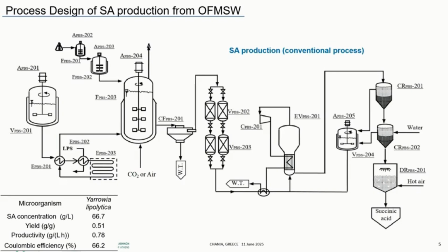In the resin columns, the salt of sodium and succinic acid, the succinate, is broken into succinic acid by anion exchange resins, where the resins absorb the sodium, and the liquid rich in succinic acid goes to the next step, which is evaporation, where the liquid is concentrated and the concentration of succinic acid increases. Then follows the step of crystallization. Here we have 2 or 3 crystallizations in order to clean the material enough, with the purity depending on the final application that we need.